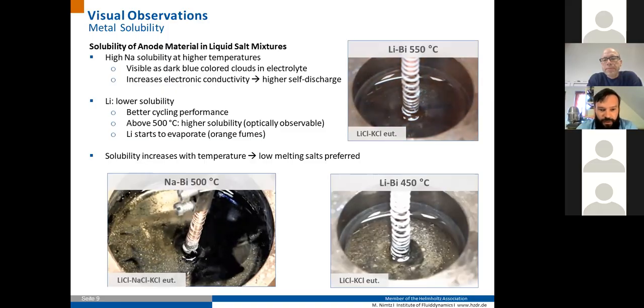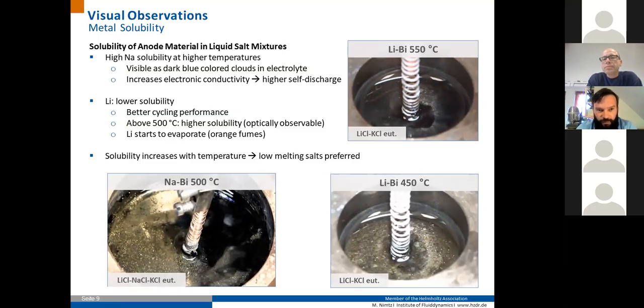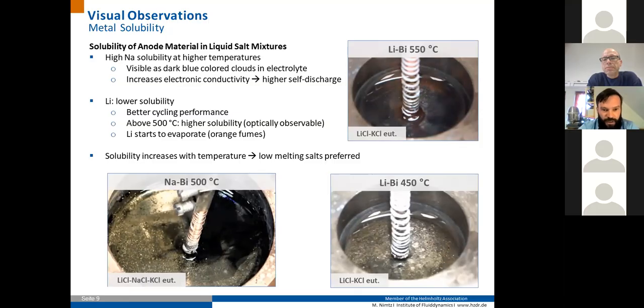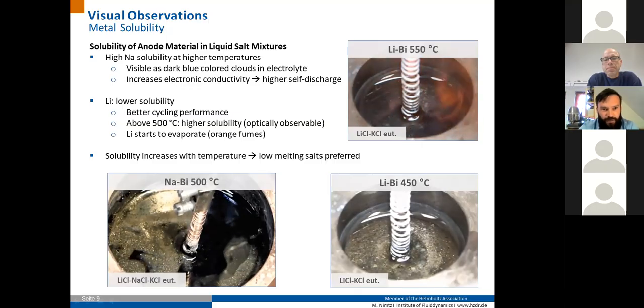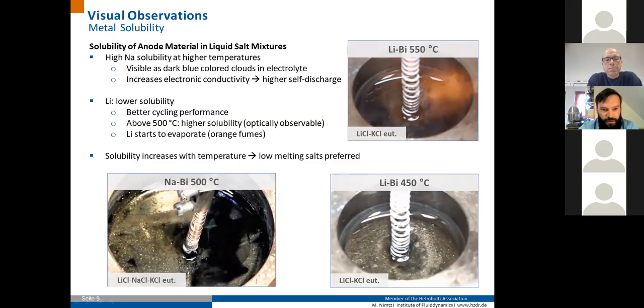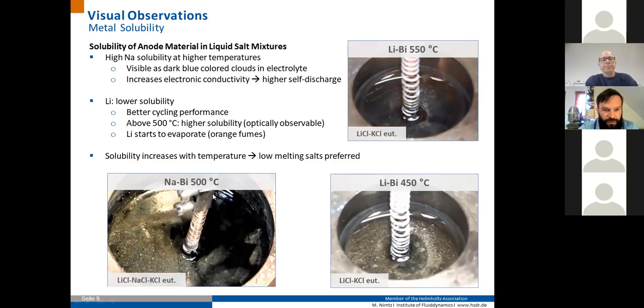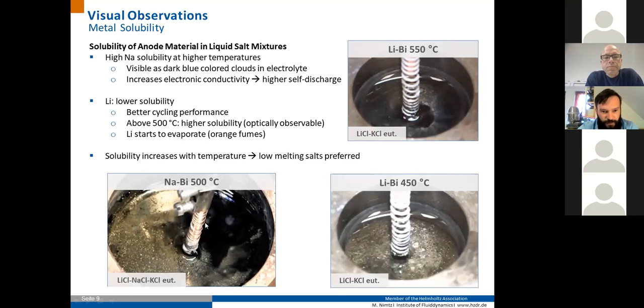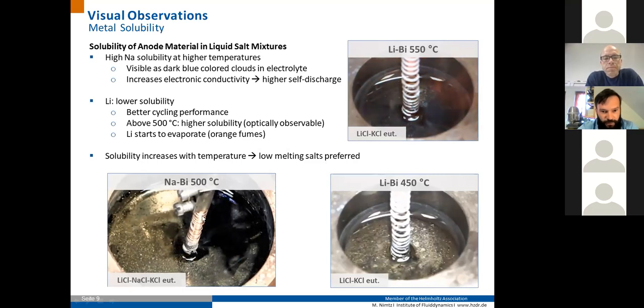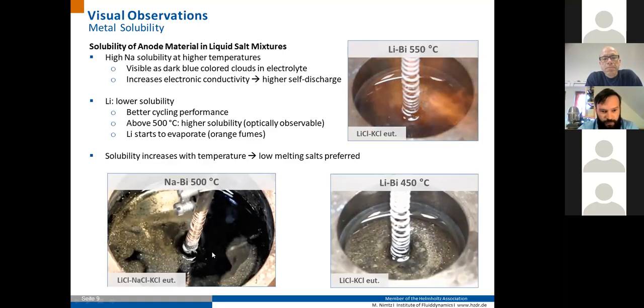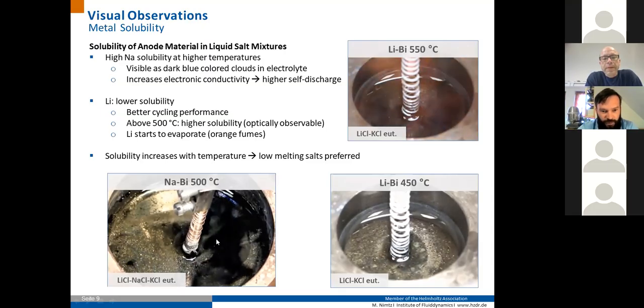Another part which has to be handled when operating liquid metal cells is the metal solubility. Some metals, like for example sodium, have a quite high solubility in the electrolyte. Here in the lower part on the left, you can see a sodium bismuth cell at a higher temperature of 500 degrees Celsius. And you can see the large clouds of dark liquid forming here. This is the sodium solution in the electrolyte, which has a quite dark color.